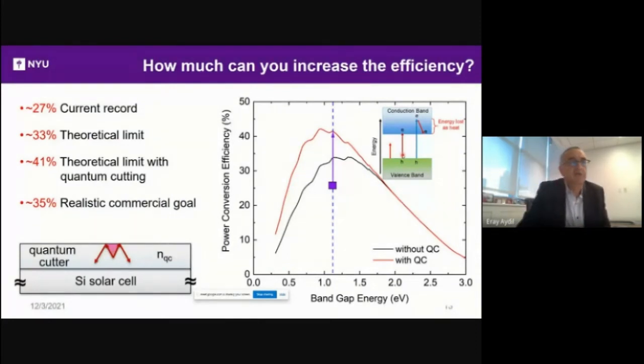So I won't bother you with the calculations, but if you sit down and repeat the calculations that were done back in 1960, you come up with the following numbers. The current record is about 27%. The theoretical limit, as I told you, is about 33%. So if you can do this quantum cutting, you can raise the theoretical limit from 33% to 41%. Okay, not all of that could be recoverable. There are all sorts of inefficiencies. So this shows here the new Shockley-Queisser limit with quantum cutting. This is where we are. So in principle, you could raise it up to here. But if you look at some realistic goals, a realistic commercial goal could be 35%, and that's still above the theoretical limit.